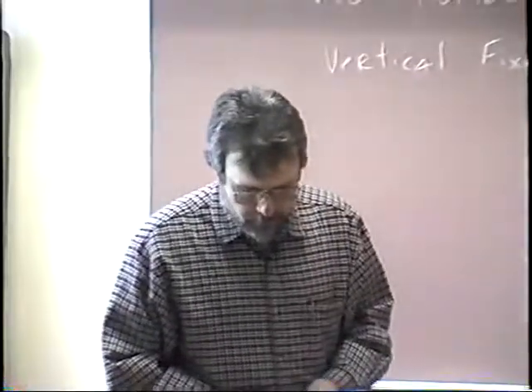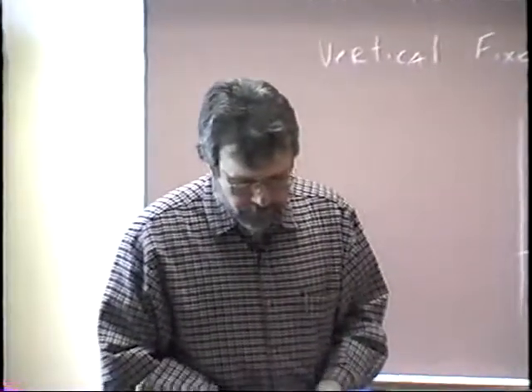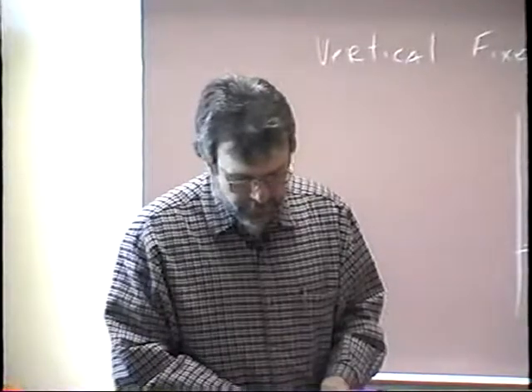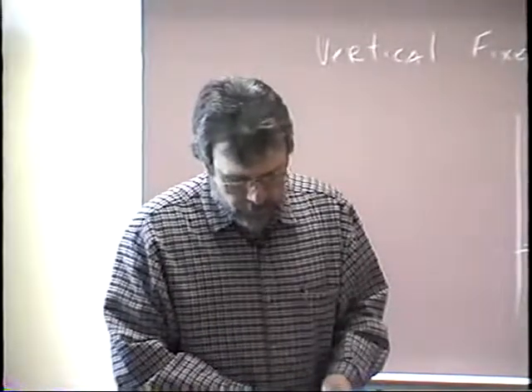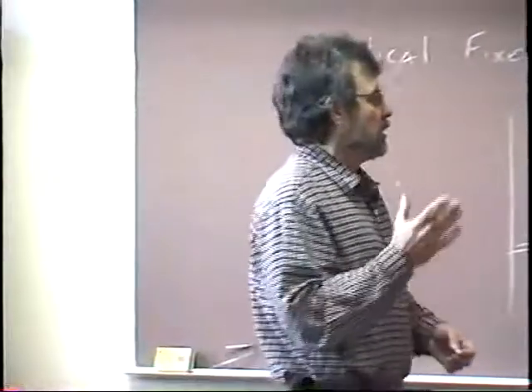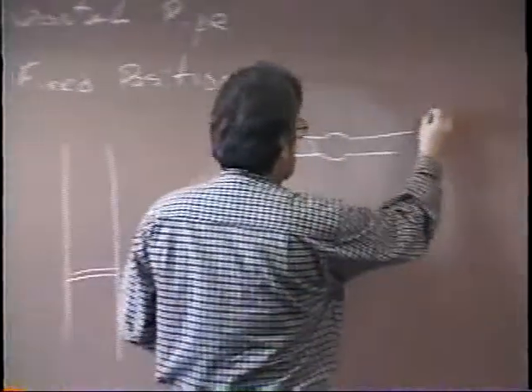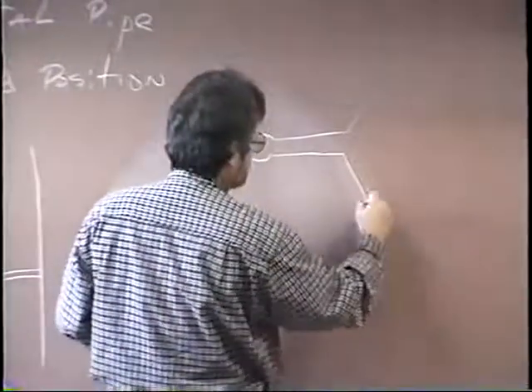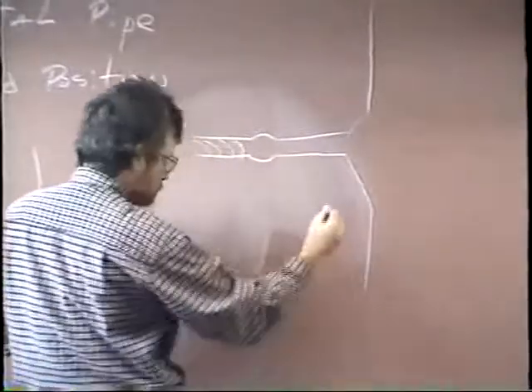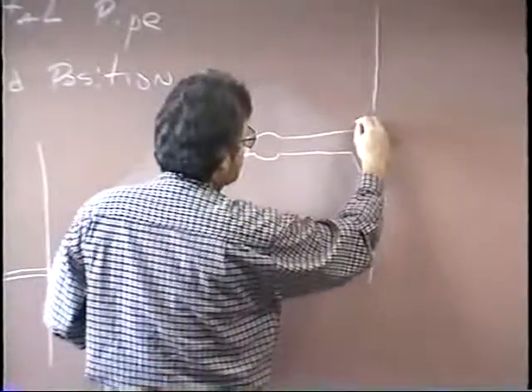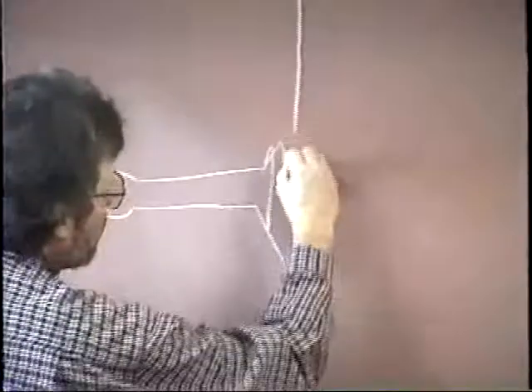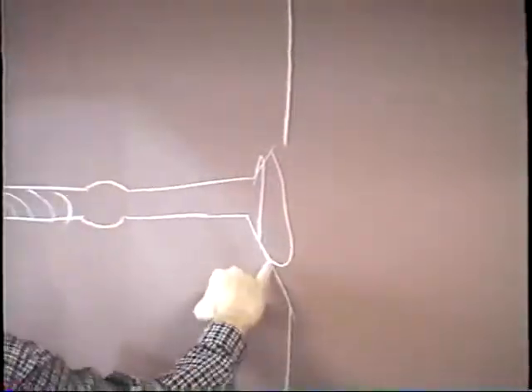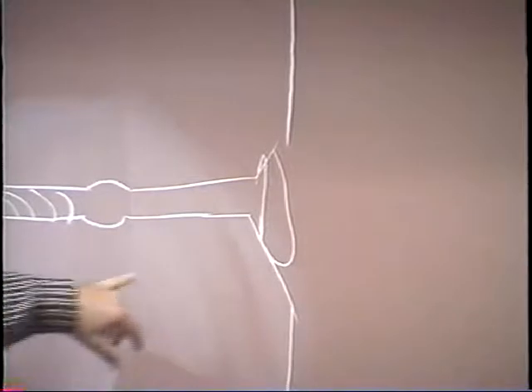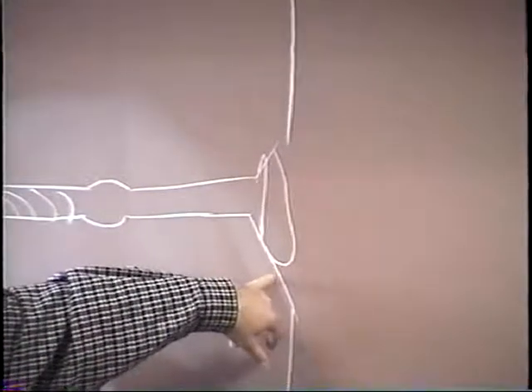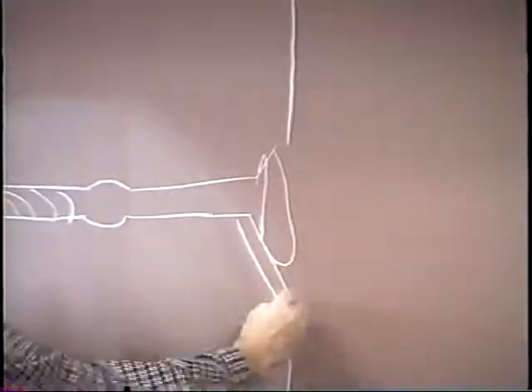Dropping down below the photograph here, it reads, the width of each bead or layer of weld metal should not exceed approximately 3 times the diameter of the electrode in order to avoid excessive weaving. Well, when I teach you how to do this, let's say this is the edge of your bevel. You can't weave it too wide. If you weave it too wide, you're going to get overlap like this. Overlap is defined as weld metal deposited in the joint that has not fused to the base metal.